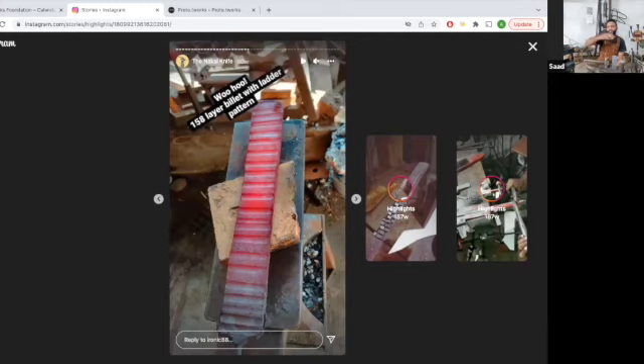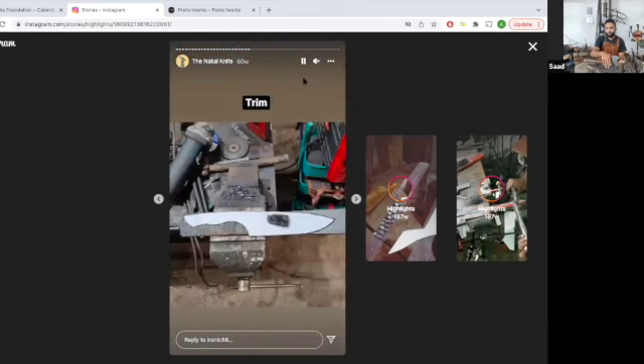So you put these indentations in this, right? And then you grind it out. So what happens is, in this specific pattern, you start off with parallel lines. But when you press these indentations in this, the parallel lines start becoming wavy. So this is called a ladder pattern, because the pattern goes one way and then it turns around, goes the other way, one way and the other way. So you can see it in the final reveal, how the pattern develops. So this is quite a simple pattern to do. This is my first time. And this is the first time I think I crossed above 100 layers for this knife.